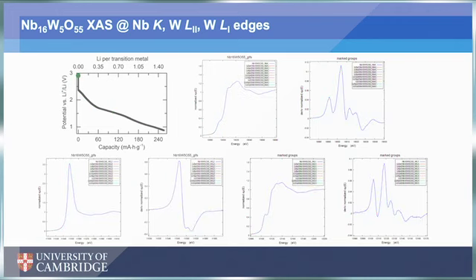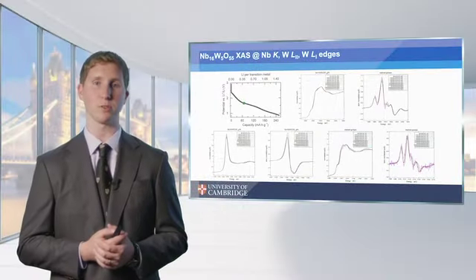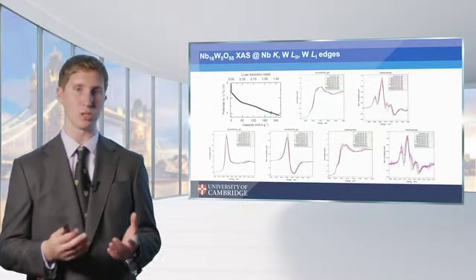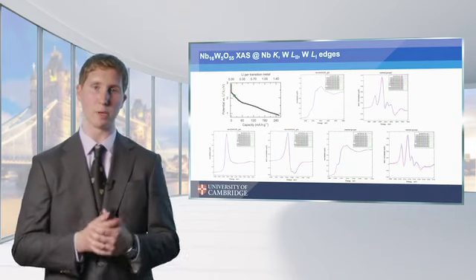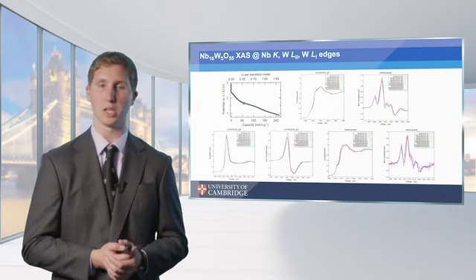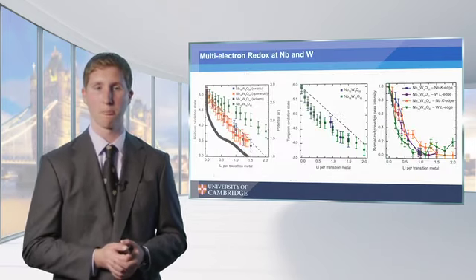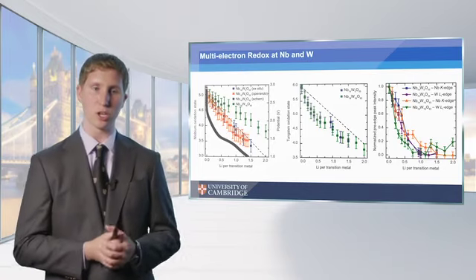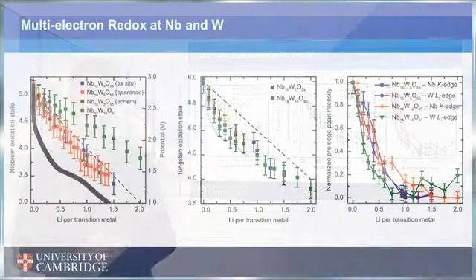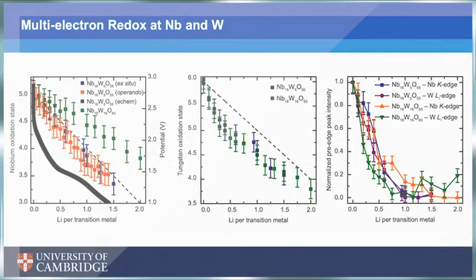So we use that as a separate measure of the reduction of each of these transition metals and an observation about the local symmetry. So we're actually observing our octahedra becoming more ordered and less distorted as we lithiate these phases. And so those data are shown here. On the left, we have the niobium oxidation state. In the middle, we have the tungsten oxidation state independently from that tungsten X-ray absorption data. And on the right, we're showing the pre-edge peak intensity, so that pre-edge feature that comes from the second-order Jahn-Teller distortion.